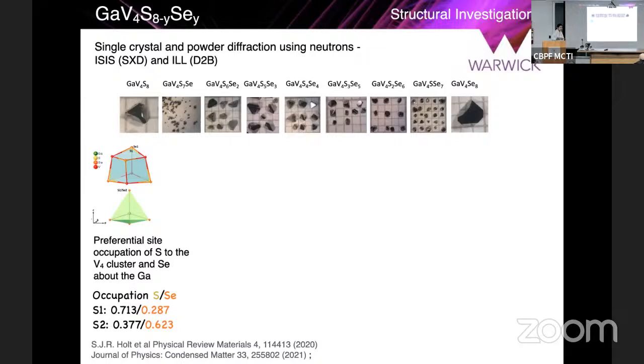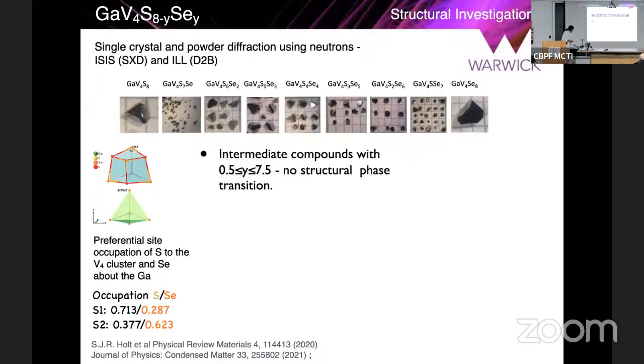Yes. So the best way to study these materials, or any materials for that matter, is to get high quality single crystals. So what we did was we produced single crystals of the entire range of materials at integer substitution steps. And these single crystals are grown by the chemical vapor transport technique. We just start off with the material, use a transporting agent such as iodine, and produce crystals. And these have been very well characterized with single crystal X-ray diffraction. So we know the exact composition of all of these, and they're very close to the starting composition.